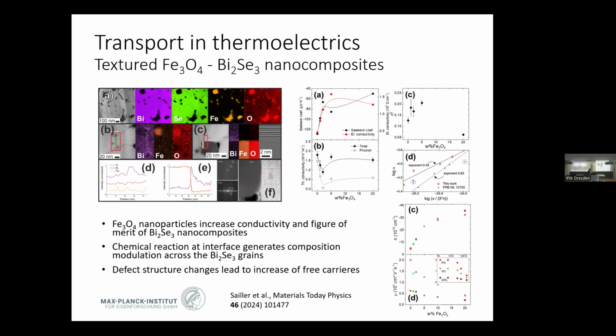So we proceed with the usual program, and then we found something particularly interesting, which was not what we expected. In this particular case, this image shows a compositional map of the transition from iron oxide to bismuth selenide. What is shown here are two lines. One is from the iron and oxygen, a very sharp transition. And the purple line, I think you see it as purple, is the bismuth.